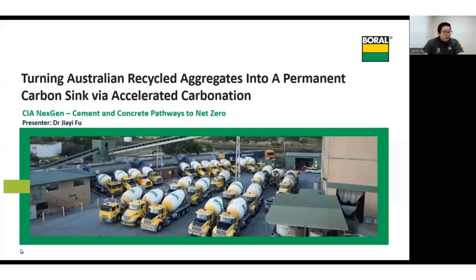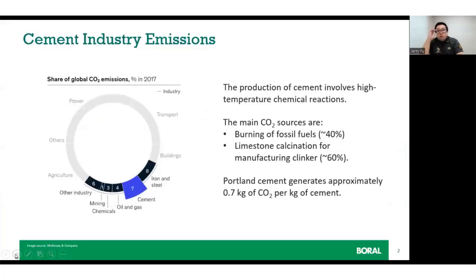So many of us have already heard that cement production is responsible for about 7% of global anthropogenic carbon emissions. More than half of these emissions are due to the release of CO2 upon the thermal decomposition of the raw material we use, limestone, during cement manufacturing. This chemical decomposition process contributes to about 60% of the total carbon emissions of the cement manufacturing process. At the same time, the fossil fuel used during the manufacturing of cement accounts for the other 40%. For every ton of manufactured grey cement, about 700 to 800 kilos of CO2 will be released.